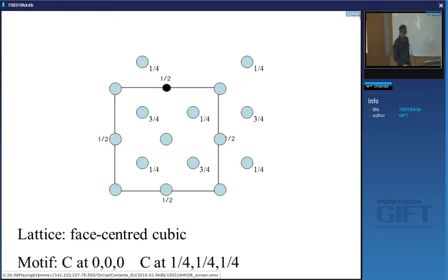And that gives us the structure of diamond. Right? So if you just focus on this part, that's the crystal structure of diamond. How many carbon atoms in there? 8, because there are 4 lattice points in the cell and we've got 2 atoms per lattice point, so there are 8 carbon atoms in there.